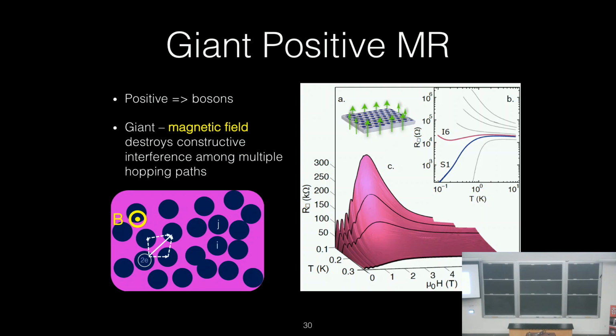If you put on an even larger field, now I'm showing you resistance, temperature, and then magnetic field to much higher field values, here are those oscillations, and then you see a giant peak in the magnetoresistance. The resistance can rise orders of magnitude in a magnetic field. In a fermionic system, if you get a magnetoresistance which is 10%, that's a lot.